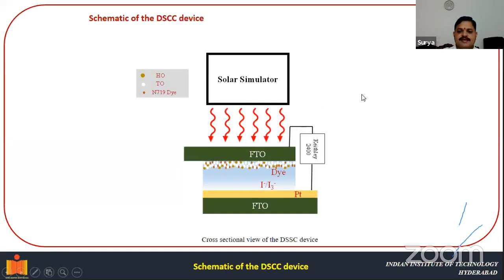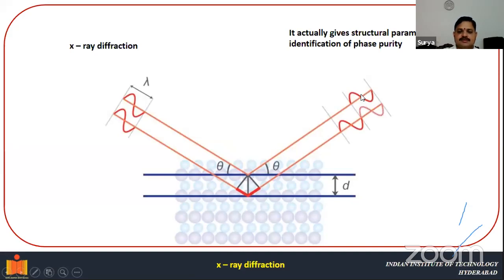Before we made this device, we also characterized our materials with various characterization tools like X-ray diffraction. X-ray diffraction gives the structural parameters and identification of the phase of the material. It gives diffraction peaks only if one condition is satisfied, that is Bragg's condition, 2d sin theta equals n lambda. Whenever the incident X-rays' wavelength matches the interplanar spacing, Bragg's condition is satisfied and it gives the diffraction pattern. From this pattern, you can calculate structural parameters like lattice parameters, bond angles, and bond lengths. So everything can be found using X-ray diffraction.